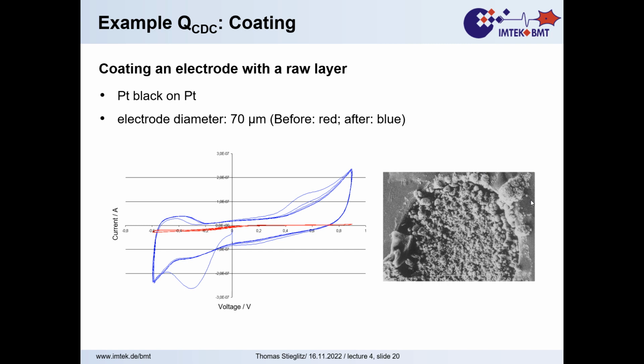Platinum black has a disadvantage because it's deposited out of a solution that contains a lot of lead. Lead is toxic. Therefore, it has been banned from any medical applications. That means for the use in humans. There have been some tricks that persons try to deposit it from a non-lead based solution where it's not that rough, and this is then called either platinum gray or platinum brown. And one of the two is patent pending. I cannot remember which one. But it's not the surface roughness, it's mainly due to the fact that people don't want to have lead in their processes.